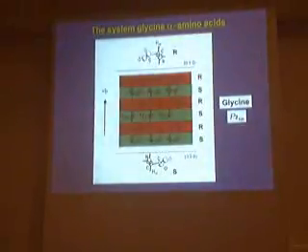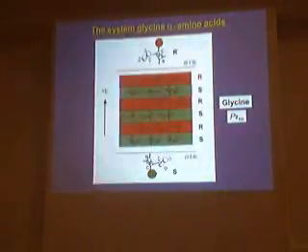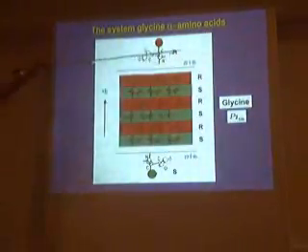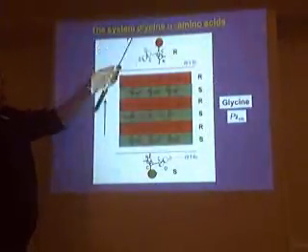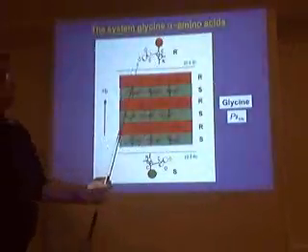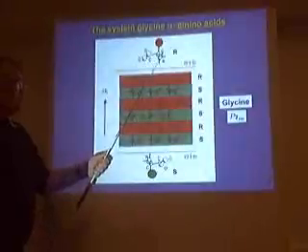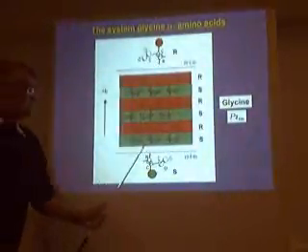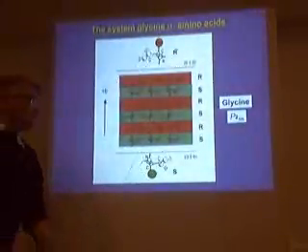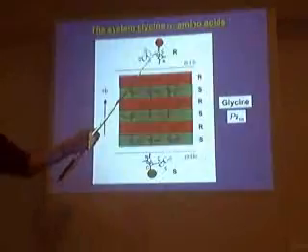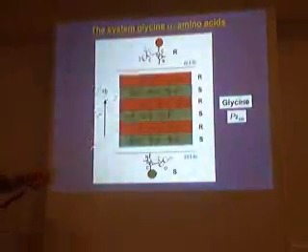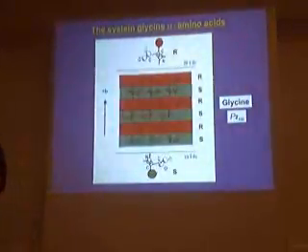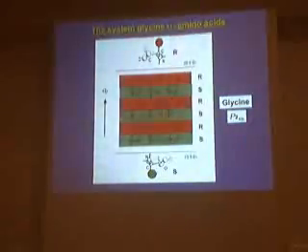What happens if I grow this crystal in the presence of any one of these alpha amino acids except glycine, right? All of them have this zwitterionic species. Okay? And in addition to this zwitterionic species, they have this group which protrudes from the surface of the crystal. But the R molecules can replace only molecules in the R layers of the crystal. Because if such a molecule came from that direction here, this surface will not recognize the R molecules. On the other hand, the S molecules can come inside from the other side. So if you grow this crystal in pure water, in the presence of DL amino acid, the DL amino acid will undergo spontaneous resolution within the crystal of glycine itself. Okay?